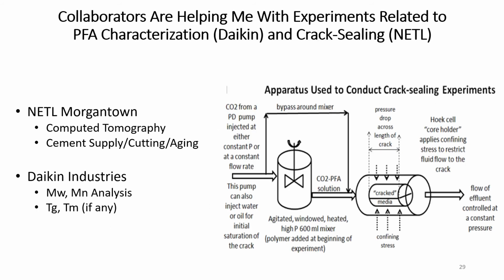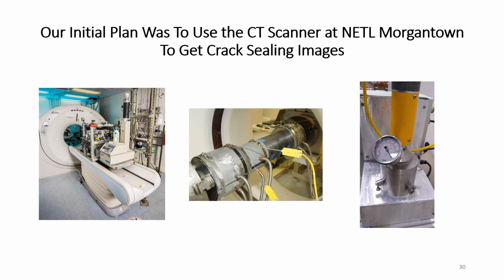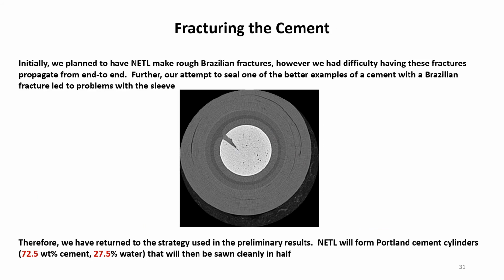For additional characterization experiments, Daikin Industries in Japan and the National Energy Technology Lab down in Morgantown, West Virginia, are providing support for me with molecular weight and glass transition analysis and cement crack sealing experiments, respectively. At first, we wanted to use a CT scanner at NETL Morgantown to get crack sealing images, but ran into a few difficulties. At high pressures, the sleeve used to keep the cement stable in the CT scanner was eaten by the crack, damaging the sleeve and making the experiment impossible to complete.